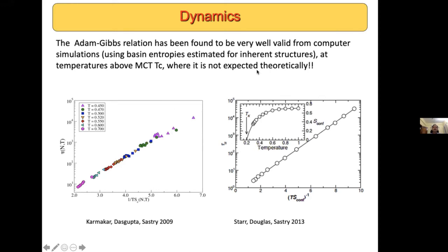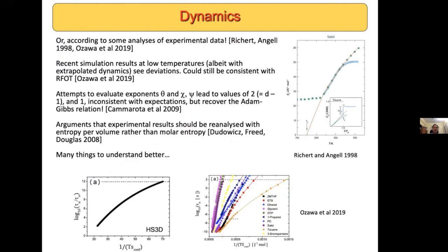It works well in a regime where it shouldn't, because from what I said, from Goldstein to the analogies with the mean field p-spin model, etc., this kind of a relationship should be valid at temperatures below this dynamical transition temperature. But one sees it working very well above, not very far above, but above. On the other hand,